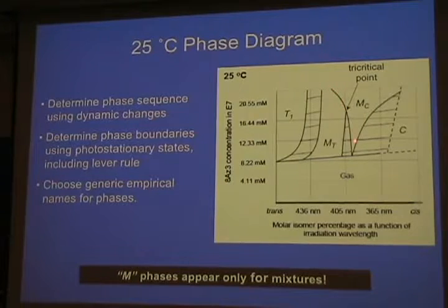And we've taken a little bit of artistic license with the really specific shapes of these boundaries because we've measured the phase behavior at various points on the grid, and so we know that the topography of this phase diagram is correct, even if we don't know exactly the shape of all these boundaries. We do see, for example, that at lower concentrations, the transition between these two mixture phases goes through phase coexistence, so it's first order, but then at higher concentrations, it's a continuous transition. So there's a lot of interesting things that we see in these monolayers, the same kind of richness that one sees in monolayers at the air-water interface.